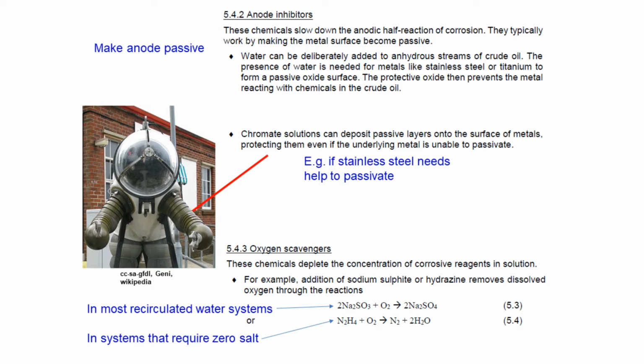You might, in that sort of system, want to have absolutely no solid salt residue able to come out of solution, in which case you can't use sodium sulfite because the sodium sulfate and the sulfite could precipitate as solids that you don't want inside the system. Therefore, you might choose to use hydrazine. You'd obviously add a very dilute amount to your water stream. The hydrazine would react, absorbing oxygen and producing only water and nitrogen gas residue, which is not going to cause solid buildup inside the recirculated water loop.